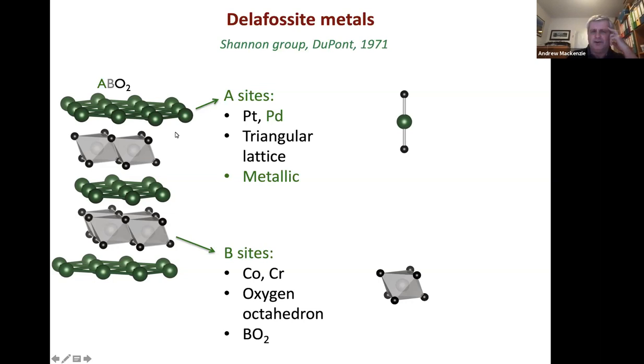And the structure, which is classically based on CuFeO2, it's an ABO2 structure where the A site atoms for our cases are going to be platinum or palladium, and they exist in two-dimensional layers on a triangular lattice. They're then interspersed with transition metal oxide layers, where the transition metal atom sits in the middle of an oxygen octahedron, but that oxygen octahedron is edge sharing, and it's edge sharing on its side, if you like, relative to the way it would be in a cuprate or a manganite or the perovskite structure.